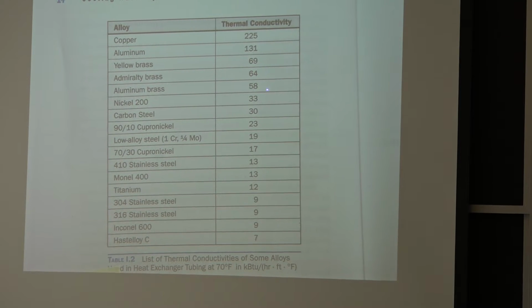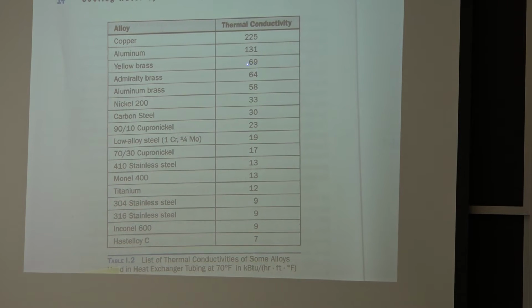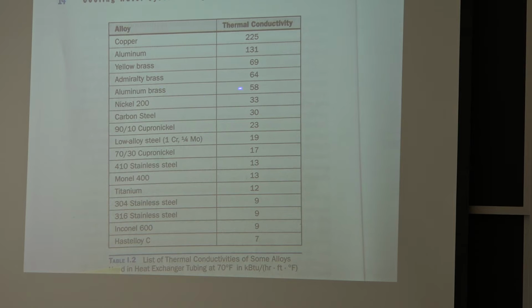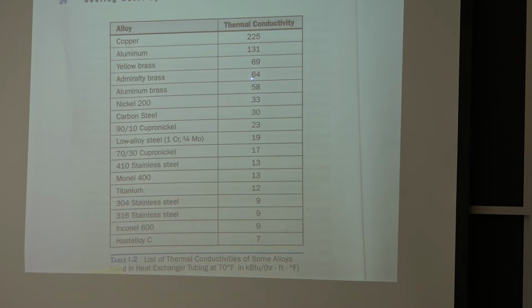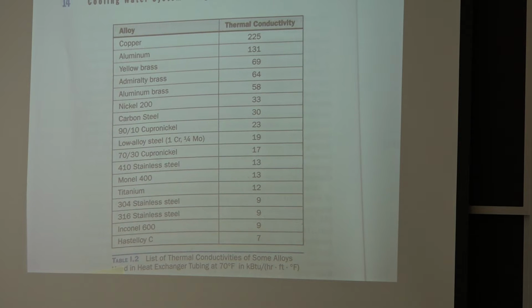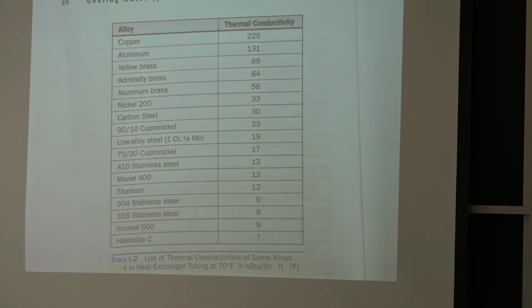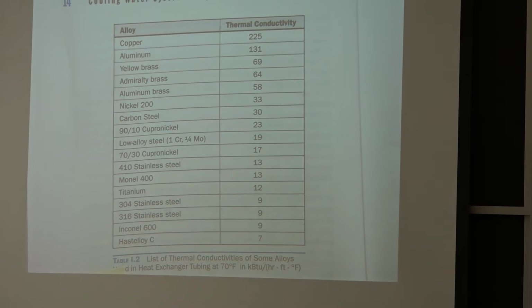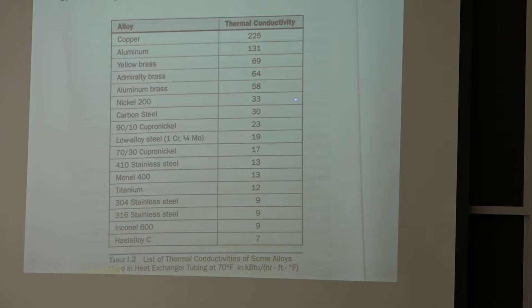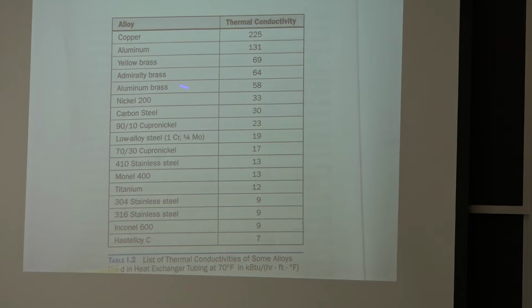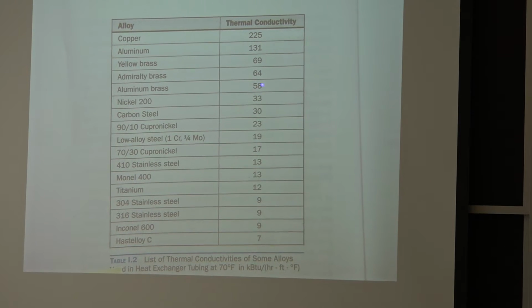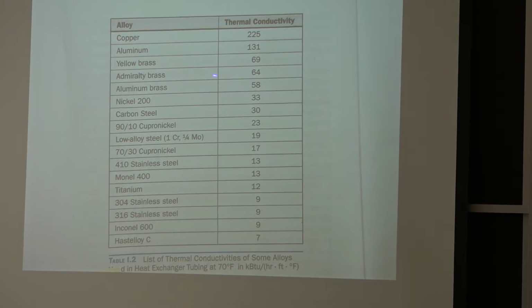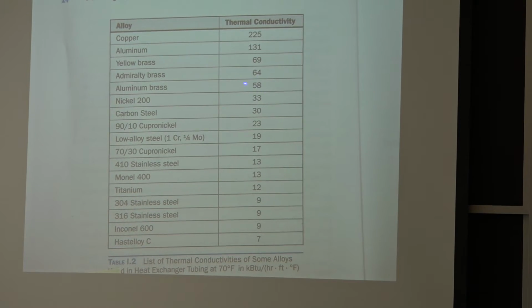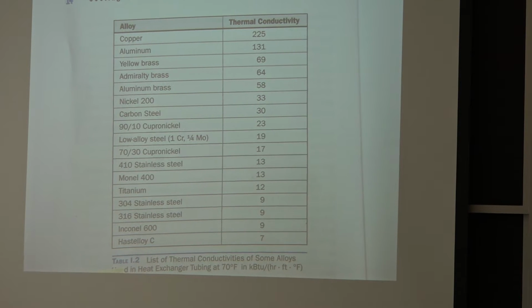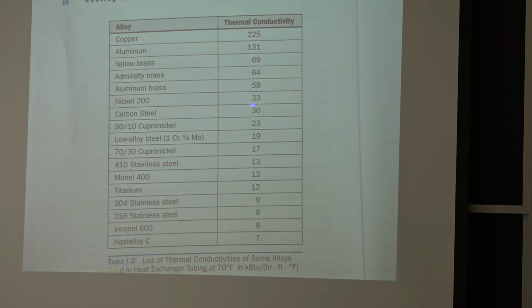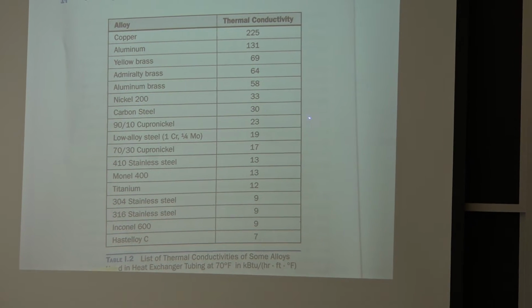Yellow brass, that's what people used to use, okay? That's number 3 in thermal conductivity. Admiralty brass and aluminum brass are alloyed a little bit. We lose a little bit, but the aluminum brass has this good aluminum oxide skin. And so it has good erosion resistance. I passed around that kind of prototype propeller. So manganese aluminum bronze is what the Navy uses for ship propellers because of the, not thermal conductivity, but erosion resistance. So that's basically what people were using, Admiralty brass, 30 or 40 years ago at Baltimore Gas and Electric, where they had this under deposit attack I was talking about. And you can use nickel, kind of pricey, but it's still got pretty good corrosion resistance.